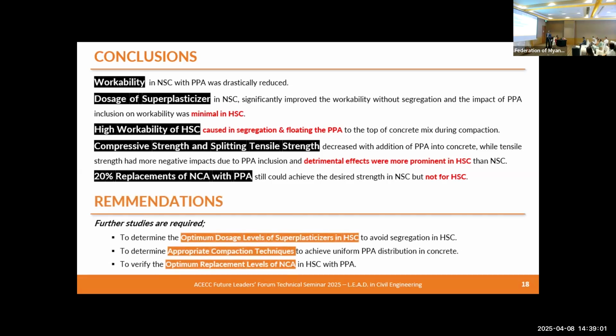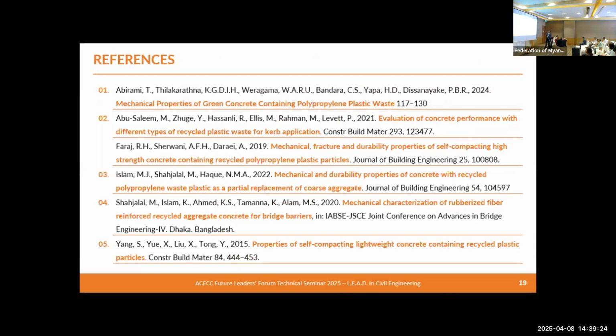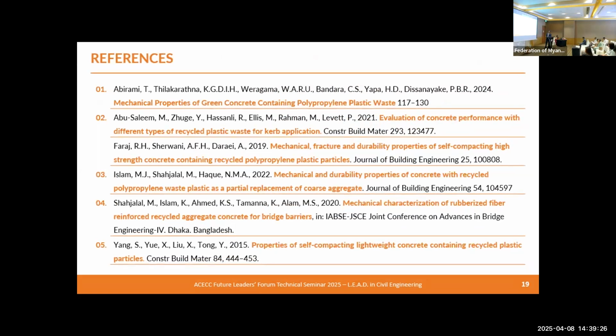So we need to check the optimum dosage of the superplasticizer, and we should incorporate appropriate compaction techniques for the high strength concrete, because segregation occurred due to the separation of the cement matrix and the plastic aggregate due to the lower density. So these are our recommendations, and these are our references that we have used.